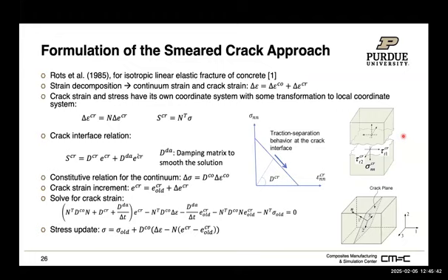One of the things we have to do is couple those residual stress predictions and defects into progressive damage. We also have to take the many modifications we did before for the progressive damage and now incorporate the residual stress, solve the convergence issue, and make sure the residual stress and the warpage are considered in the right way.